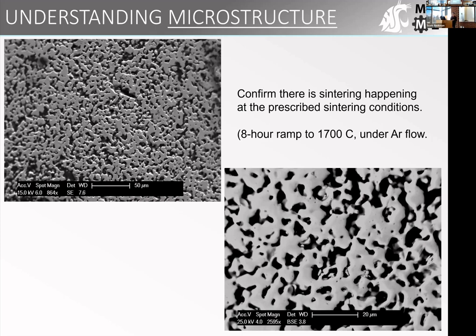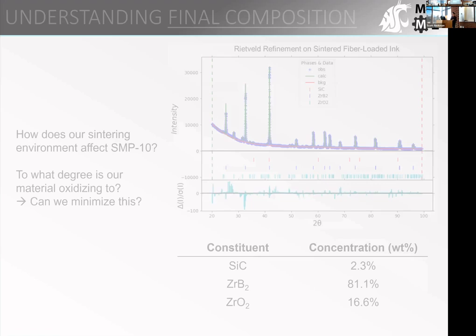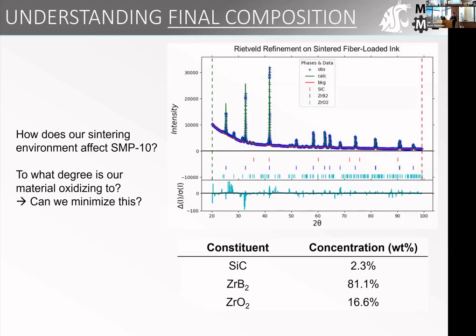The lighter particles here are our zirconium diboride. So we were satisfied with the microstructure that we saw, and we wanted to characterize the composition that we were left with as well. And we did that doing some Rietveld refinements on XRD patterns. We basically wanted to find out, of course, what our composition is, but also how much are we oxidizing, because we know we're going to be oxidizing, and can we minimize the oxidation we're seeing.